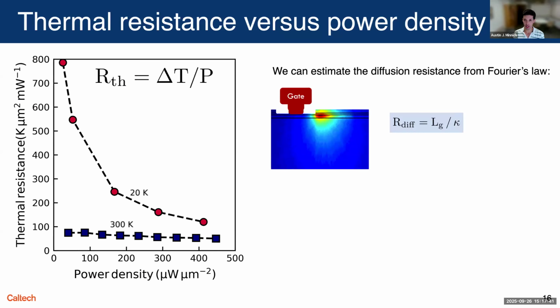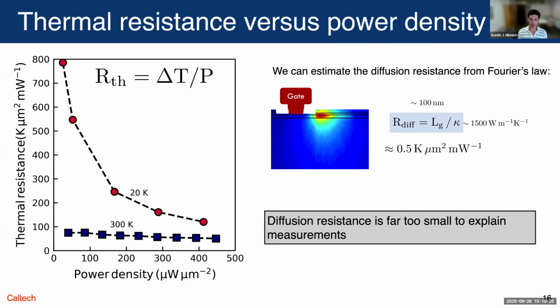Okay, so now looking to the right of the slide, we can try to understand what mechanism could cause this, first by estimating the thermal diffusion resistance from Fourier's law. And the expression for that is given in the box. It's the gate length over kappa approximately. And if you plug in numbers for the gate length, these are all hand-waving estimations, but it gives the scale. You get a number which is 0.5 in these units. And if you put 0.5 on the scale of the plot on the left, it's not even on the plot. It's basically at the bottom at 0. So what that says is that heat diffusion resistance is way too small to explain what's measured under these conditions at cryogenic temperatures.